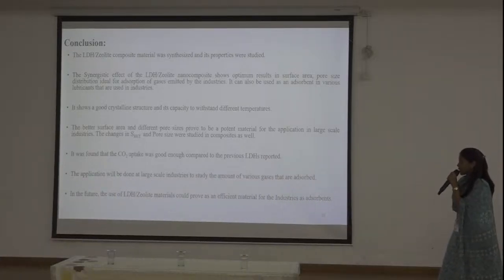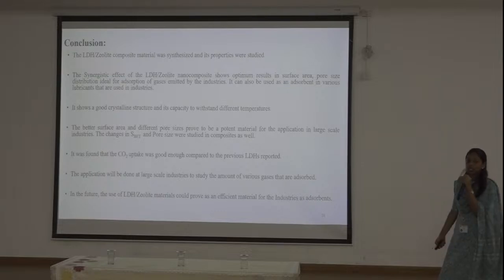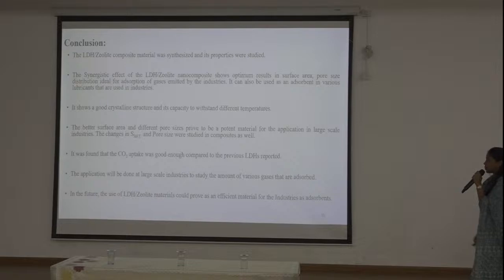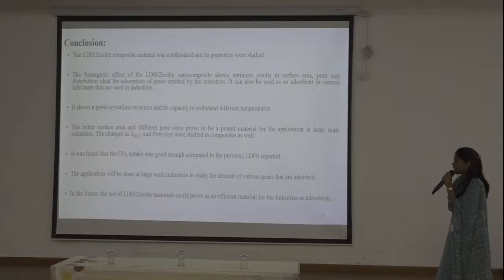Also, the SBET and pore size prove this to be a potent material for application at large-scale industries that are emitting CO2 precisely. It was also found that the carbon dioxide uptake was good enough compared to previous layer double hydroxides and zeolites.